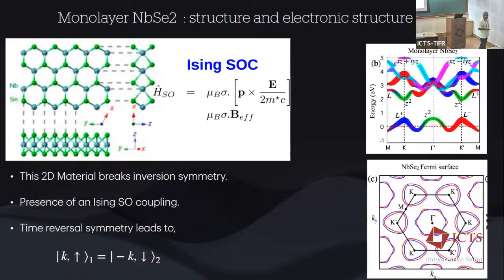Now, what that leads to is effectively the lattice structure for this 2D material that you have. This is a side view of this particular structure. The lattice structure of this 2D material breaks the inversion symmetry for this particular system. So this is a non-centrosymmetric crystal structure. But additionally, although it is a non-centrosymmetric crystal structure, if you look at the side view of the niobium and the selenium layer, you can see that there is a planar reflection symmetry about a plane like this.